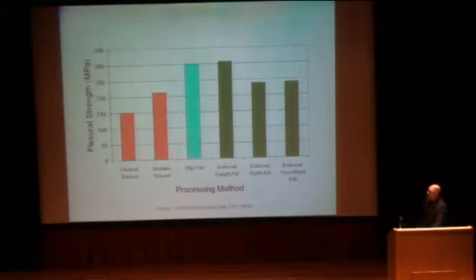The other thing, like I alluded to, is that you're going to have microscopic defects between the layers. So what we did is we tried to see how bad it would be by looking at the flexural strength of bend bars versus the processing method, with the more traditional ceramic processing techniques of pressing, isopressing, and slip casting. Slip casting typically has the highest strength. And what we found is that with Robocasting, it's a lot like composites where you have directionality because of the micro defects between the layers. So if you break the part lengthwise to the build direction, you can get strengths comparable to slip casting. But if you start breaking in directions perpendicular to your build, then all these little defective areas come into play when you try to bend that thing, and you'll actually reduce the strength by about 20%.